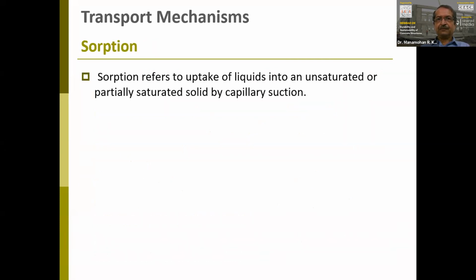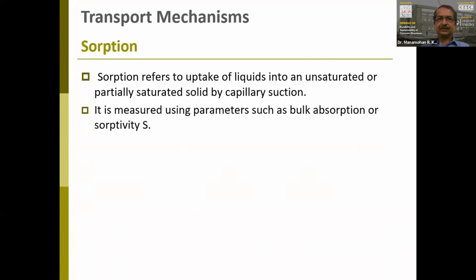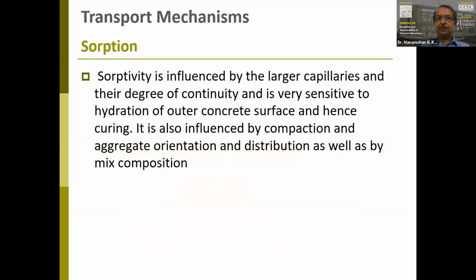Sorption refers to the uptake of liquids into an unsaturated or partially saturated solid by capillary suction. So this is another mode by which the ingress can happen. It is measured using parameters like bulk absorption or sorptivity. Again, there are equations for this. Sorptivity is influenced by larger capillaries and their degree of continuity, and it is very sensitive to hydration of the outer concrete surface and hence the curing. So it's influenced by compaction, by curing, and the aggregate orientation and distribution, as well as by mix composition.